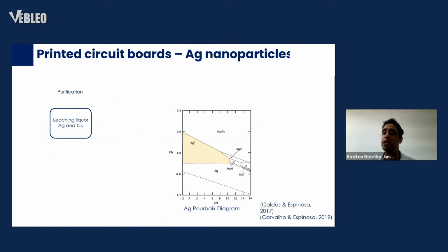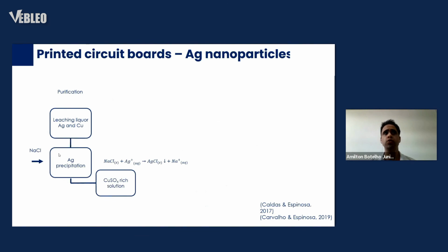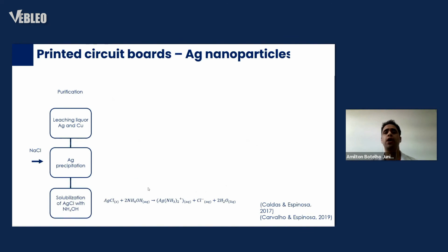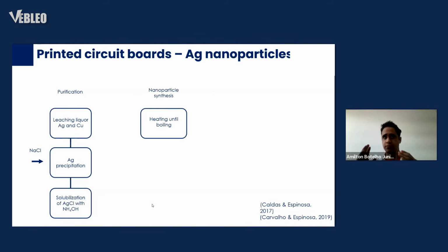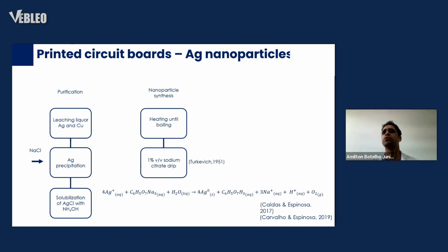Okay. Another possibility is to obtain silver from PCB and also synthesize silver nanoparticles. So after the leaching, in the leach solution, silver is recovered using sodium chloride, and then a concentrated copper solution is obtained here. And then silver is solubilized using ammonium hydroxide, and then silver nanoparticles are synthesized by the Turkevich method.